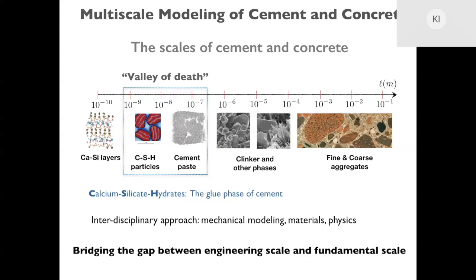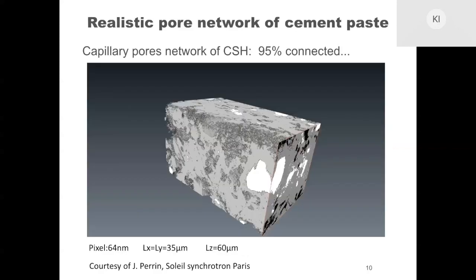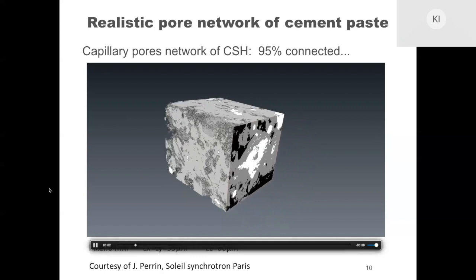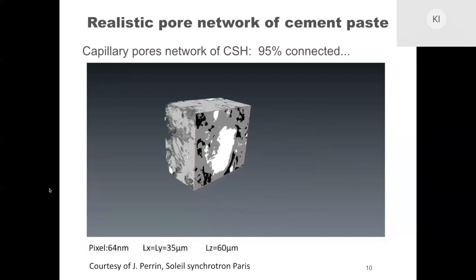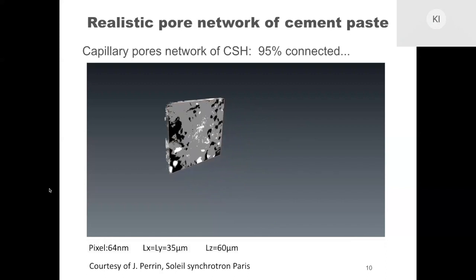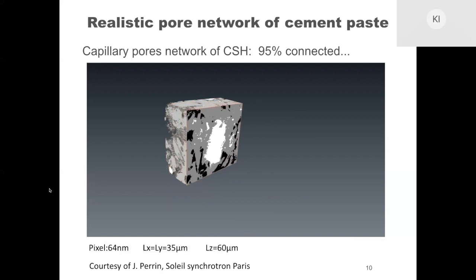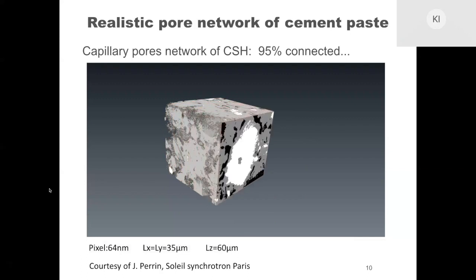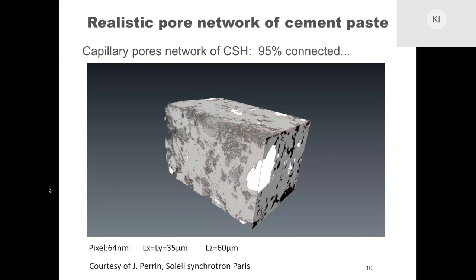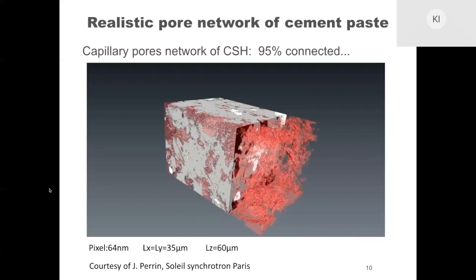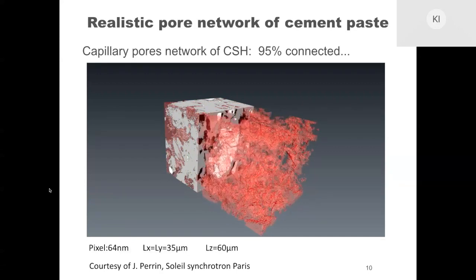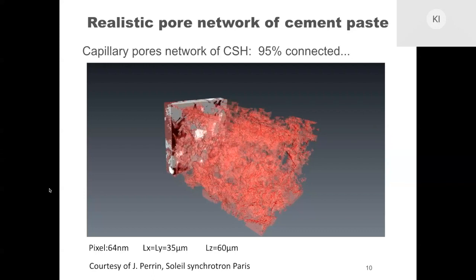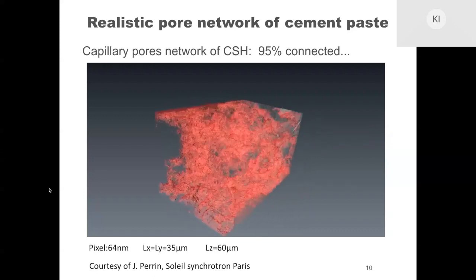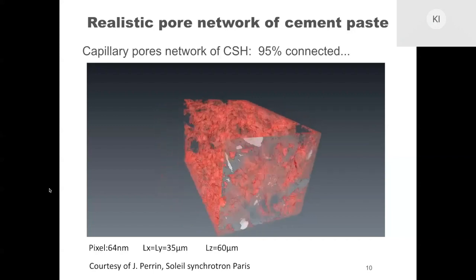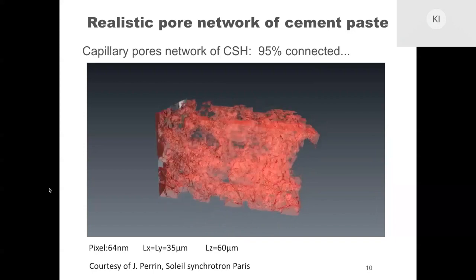I will start by showing you an X-ray tomography of a piece of cement. Here you see a piece of cement, we are scanning it through. The white part is the unreacted clinker, the gray part is the cement paste, and the black is the porosity. The pixel resolution is 64 nanometers, and this was a slab of 35 by 60 micrometers. The red network that you see here is the pore network of cement. As you can see, it's very complex, it's very tortuous, and actually it's connected up to 95%.